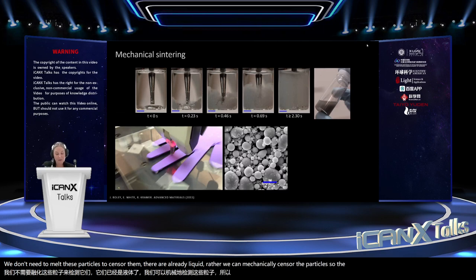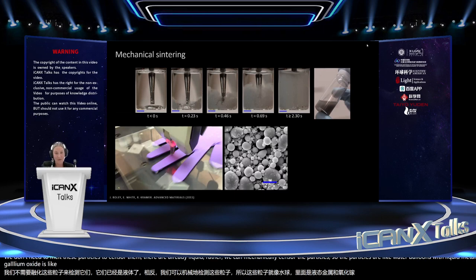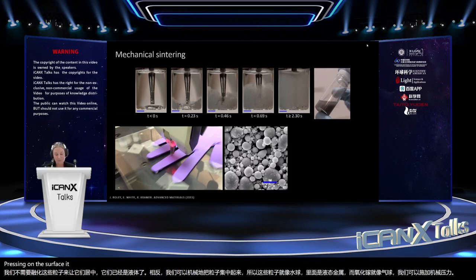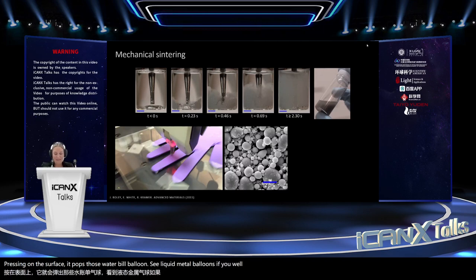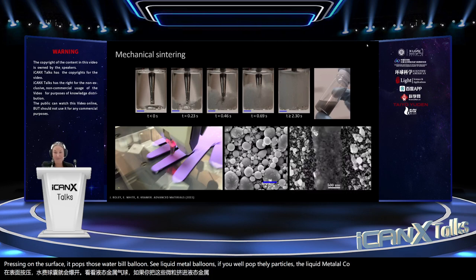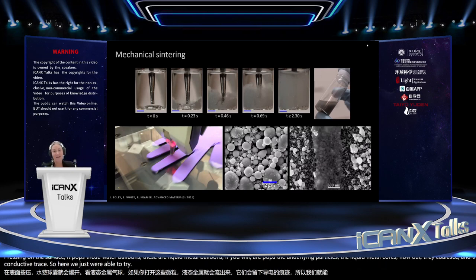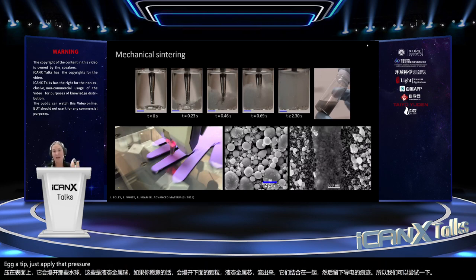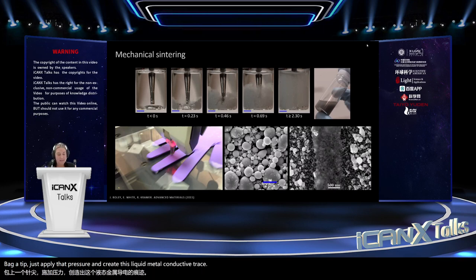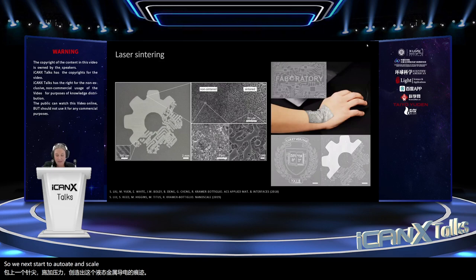So the particles are like water balloons with liquid metal on the inside, and the gallium oxide is like the balloon. And we can apply mechanical pressure, just pressing on the surface. It pops those water balloons, these liquid metal balloons, if you will. It pops the underlying particles, the liquid metal cores flow out, they coalesce, and they leave behind a conductive trace. So here we just were able to drag a tip, just apply that pressure, and create this liquid metal conductive trace. So we next sought to automate and scale the printing and sintering process.